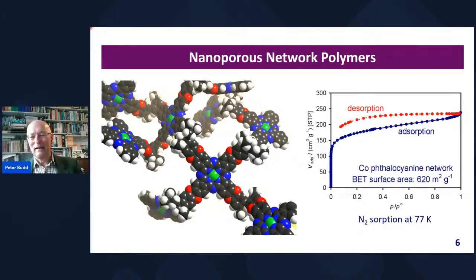Now, if we do something like nitrogen absorption, desorption, liquid nitrogen temperature, what we can see is very strong absorption at very low relative pressure. This is typical of what people in the absorption field call a microporous material. In this context, microporous means that we have pores less than a couple of nanometers in dimension. And the importance of those very tiny pores, less than a couple of nanometers, is that if you have a small molecule sat in that pore, it feels the walls all around it.